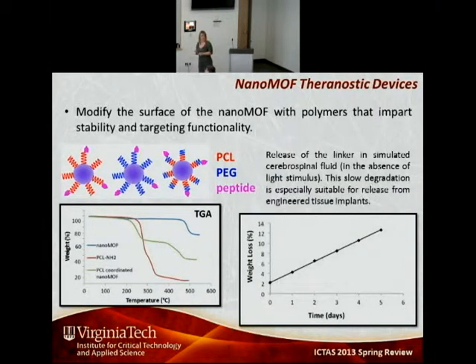And so here in this picture, we use thermogravimetric analysis to show that we attach this polymeric shell to the nanoparticle, and now we can look if the coating with a polymer shell actually improves the stability of the nanoparticle. And here we're looking at a version where we have a polycaprolactone as a shell.